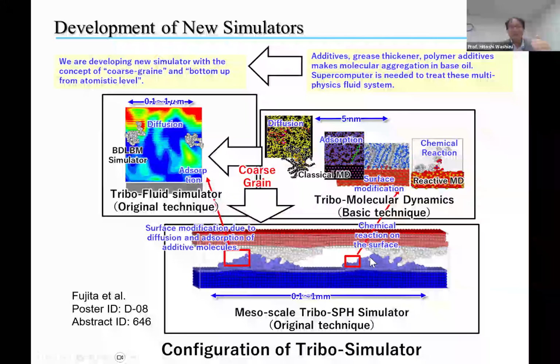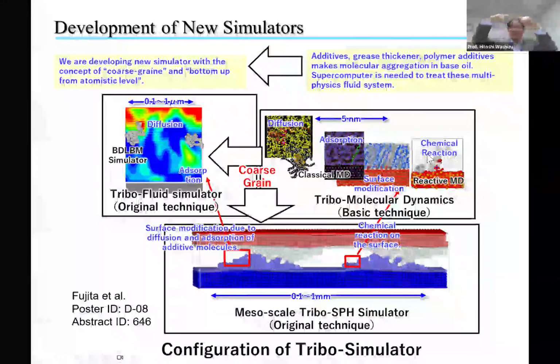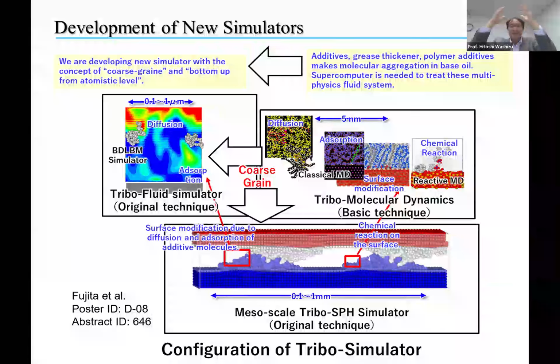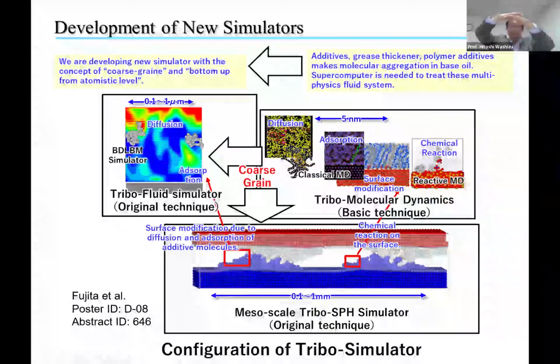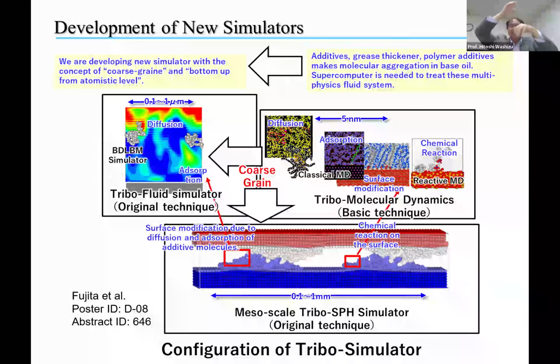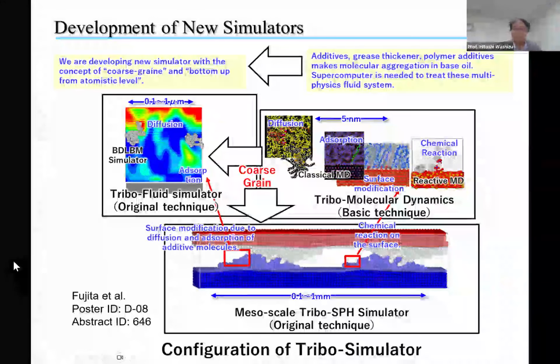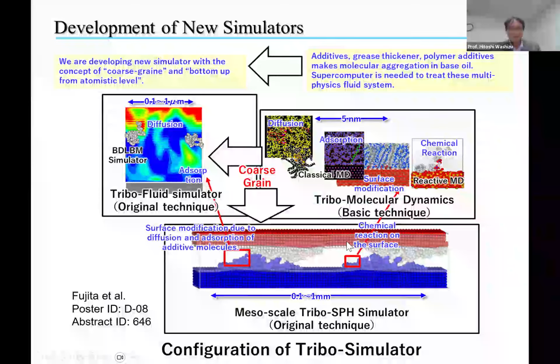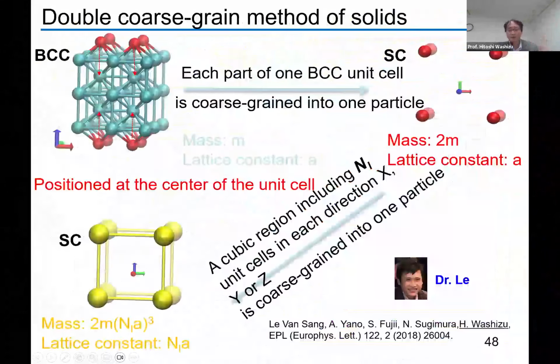But tribology effects happen in a much larger system, like 1 millimeter or sub-millimeter. If we rub metal on metal at very high load, heat is generated and the temperature grows. We call this the real contact area. In the real contact area, at first there is very mild friction, but heat is generated and comes into the surface, and then on the second contact, third contact, something wrong happens or not. So to understand this phenomenon, we need to make a much larger system. So we need to coarse grain the solid materials.